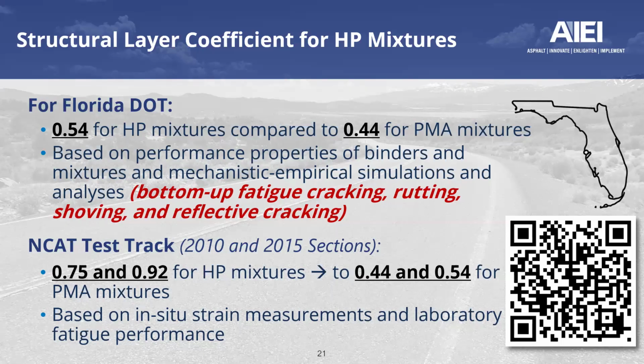Also, the NCAT test track has a lot of follow-up studies, with sections and analysis between 2010 and 2015 on top of the 2009 section. They recommended structural layer coefficients of up to 0.75 and 0.92 when HP mixtures are being used, compared to the 0.44 and 0.54 conventionally used for PMA, respectively. All of that was determined based on in situ strain measurements and a lot of lab fatigue performance.